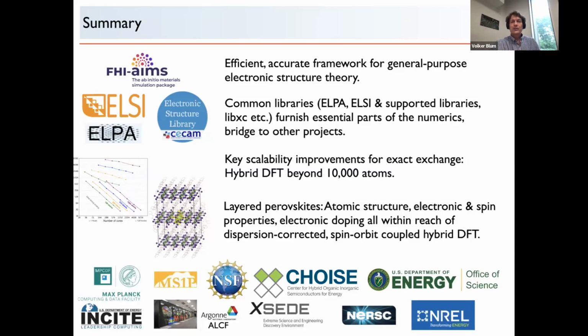Well, you can look at the benchmarking literature, right? In the case of the Delta test, there were numerous pseudopotentials that were simply wrong in the literature. And yes, you can probably parameterize a pseudopotential for every element, but I had this experience early in my career that I had to test the pseudopotentials, and if I didn't test, I would run into errors. I'm sorry about this, but this is so, right? And so in the context of the Delta project, the Science paper that I mentioned, the various pseudopotential sets improved. But if you do something like lithium, for example, this is a random example, right? And you use a standard pseudopotential that was out there that seemed to be good. Lithium is very sensitive. And it turns out that this is a very soft material and you could get huge errors in the lithium pseudopotential. And I wonder how many were out there.